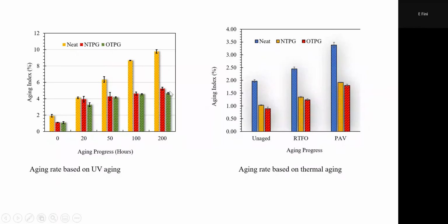You can see they're aging nearly the same, but all of them much better than the neat. So the addition of the plastic, it might be because the plastic is actually working as a sacrificing agent, helping delay the aging of the bitumen as a whole. Same thing with thermal aging.